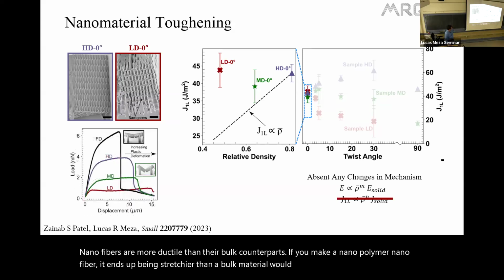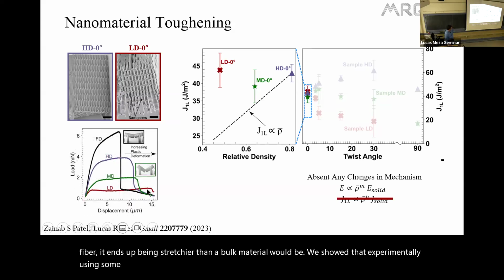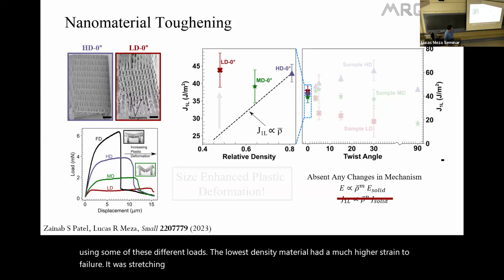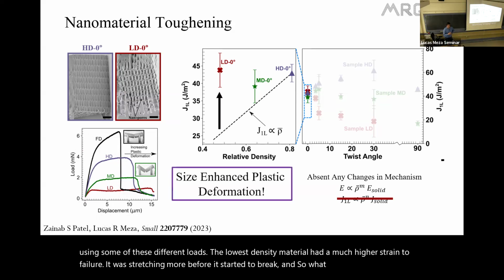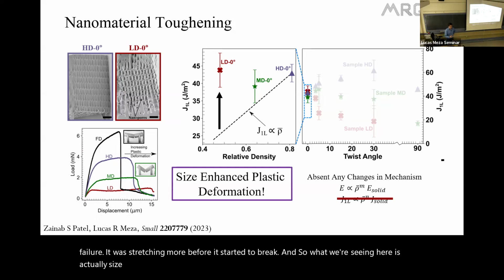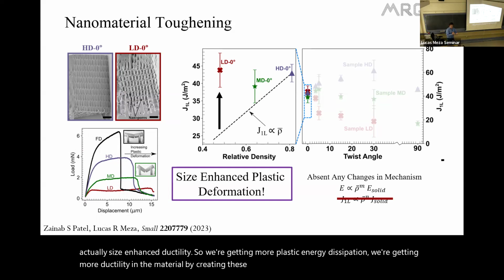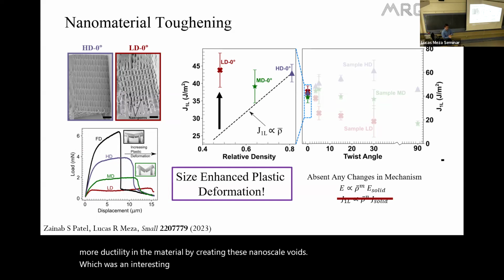We showed that experimentally using some of these different loads. The lowest density material had a much higher strain to failure. It was stretching more before it started to break. And so what we're seeing here is actually size-enhanced ductility. So we're getting more plastic energy dissipation, we're getting more ductility in the material by creating these nanoscale voids, which was an interesting first result. But why? Why is it more ductile? So that's where we got stuck on next.